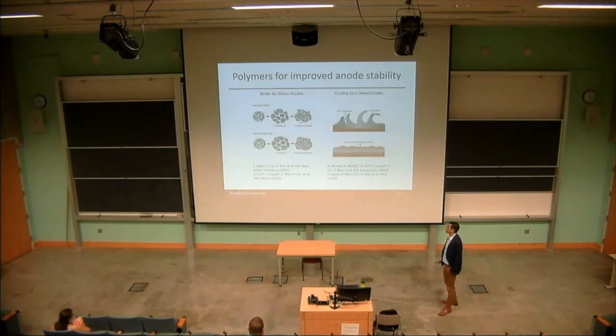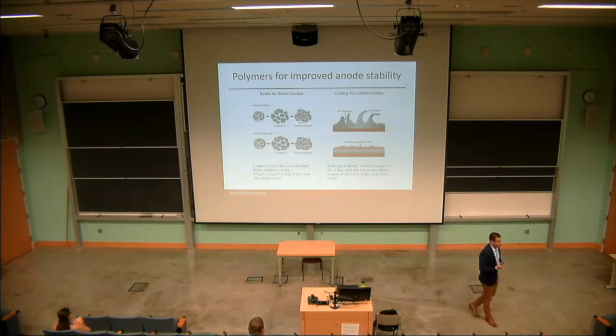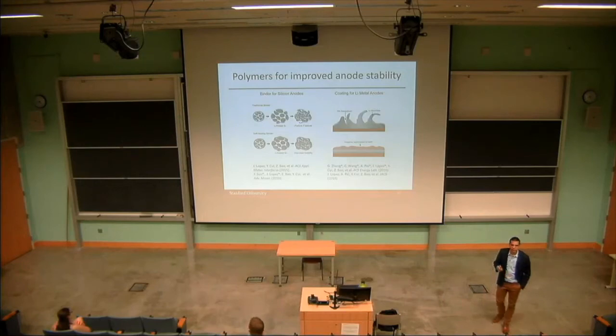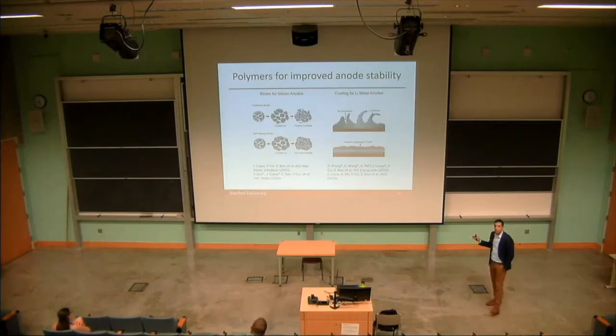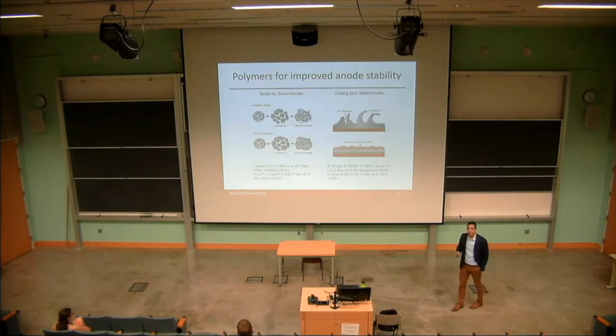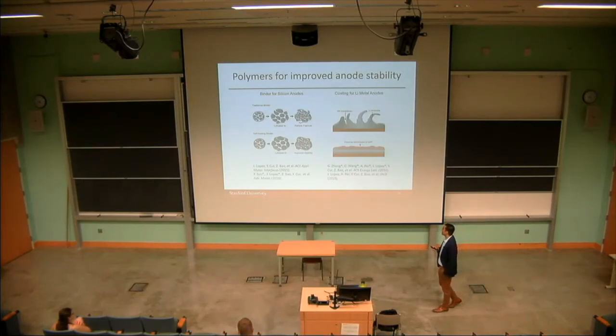So just to summarize, I started off by talking about our self-healing binder for silicon electrodes and understanding the mechanical properties of these binders and what allows them to function as self-healing materials for silicon. Then I talked a little bit about how we adapted that coating to lithium metal, and then ended with the fundamental understanding of these coatings on lithium metal and finding dielectric constant and surface energy as two really key parameters from the polymers in order to stabilize and design better coatings.